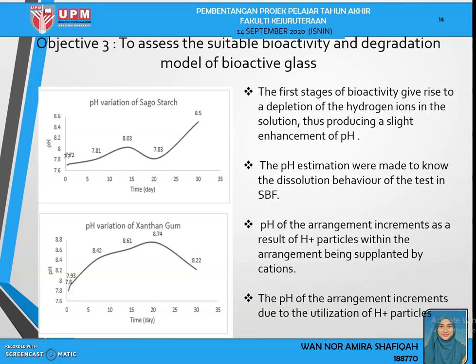The third objective is to assess the suitable bioactivity and degradation model of bioactive glass. We have the pH variation here for sago starch and xanthan gum. Note that the first stage of bioactivity gives rise to a depletion of the hydrogen ions in the solution, thus producing a slight enhancement of pH. The pH estimation was made to know the dissolution behavior of the tablet in the SBF. If we compare between the two, the dissolution behavior of xanthan gum is higher compared to sago starch.